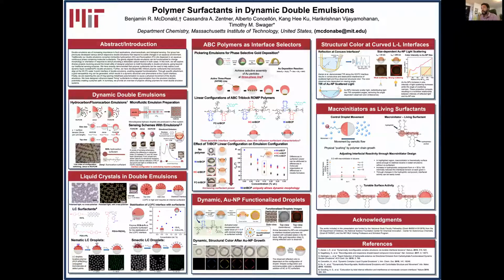configuration. And so we make these really beautiful monodispersed materials, as we call them, that pack in these hexagonal structures using a microfluidics platform. All we do is take these two constituents and heat them past their critical mixing temperature, so instead of being two phases, they're one.